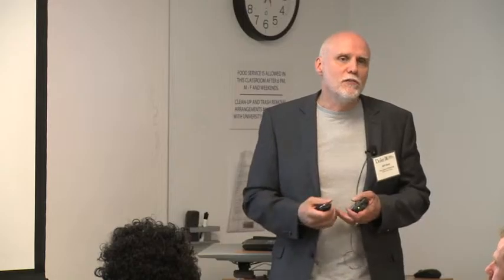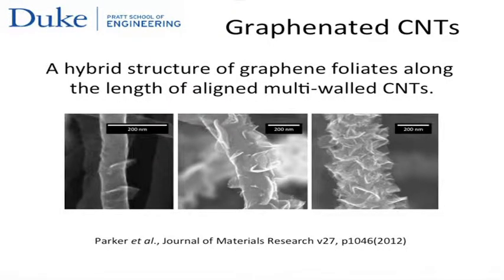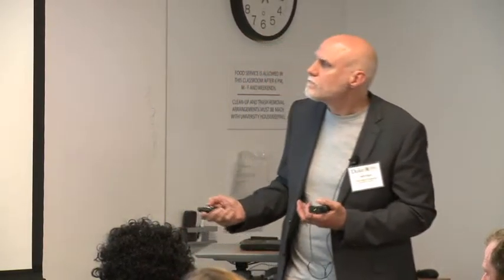Here's our kind of our bread and butter right now, and that's graphenated carbon nanotubes. So we grow graphene foliates or flakes all along these carbon nanotube structures. So we have a carbon nanotube, and then we grow these flakes, and that gives it much higher storage capacity for energy storage and gives it much higher catalytic capabilities for catalysis.